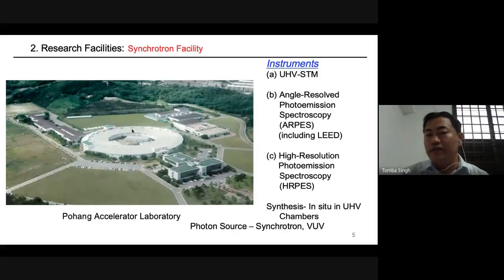In our beamlines, we have ultra-high vacuum facilities, so we have UHV STM, scanning tunneling microscopy, and ARPES, angle-resolved photoemission spectroscopy. There are many accessory units, like a low energy electron diffraction system, and for core level study, XPS, X-ray photoemission spectroscopy, is very appropriate. To be specific, the instruments we use are hemispherical electron analyzers. I think you have seen them in XPS systems also. That's very similar. Here we use a Scienta R4000. They are very good electron analyzers. We can reach a resolution of around 50 milli electron volts at 34 electron volt photon energy.